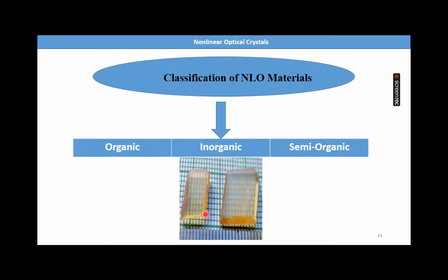The best non-linear materials are inorganic crystals like KDP, ADP, and KTP that are increasingly used in electro-optical applications as well as second harmonic generation. The most popular crystal for second harmonic generation is potassium dihydrogen phosphate, which has a broad transparency range, good birefringence, and a modest optical damage threshold. After numerous attempts, excellent non-linear borate crystals with a wide range of transparency have been found.